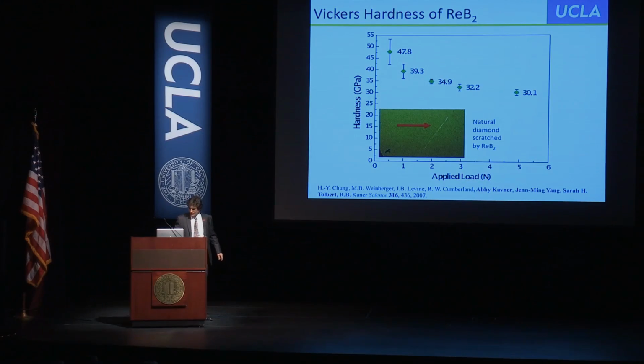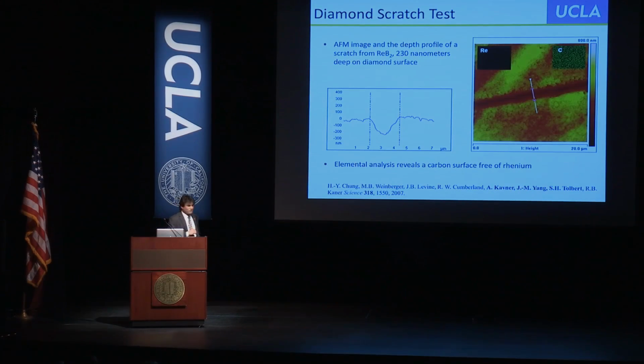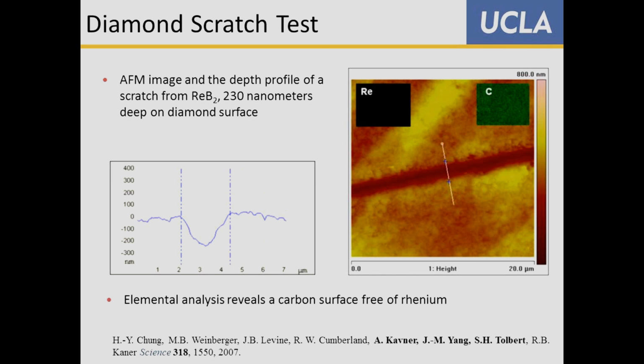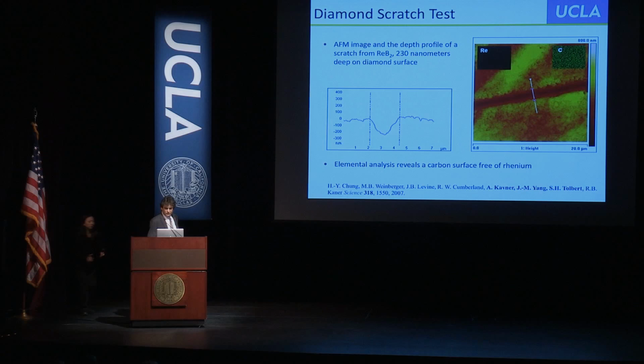So we discussed it, and we figured out that it has an angular dependence. And if you get the right angle, you can take our rhenium diboride and put multiple scratches in diamond. So we put another scratch in diamond, and we sent it back, and reviewers decided this was really interesting. So here's another paper that appeared in Science. And this is the diamond surface as measured using atomic force microscopy. And you can see the gouge, and here's the profile. You can see we put a nice scratch in the diamond.